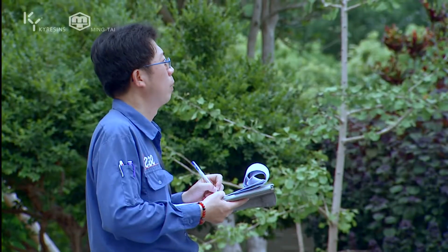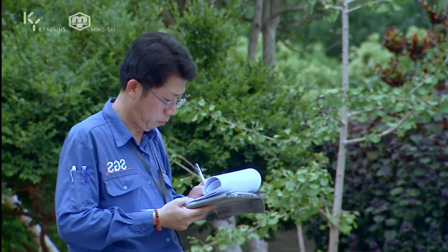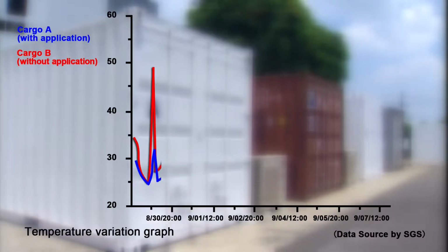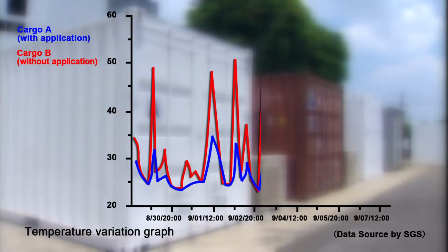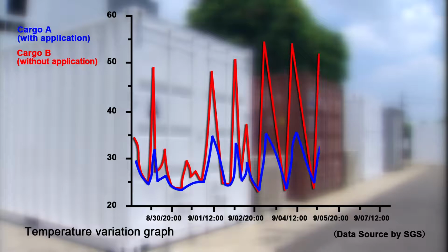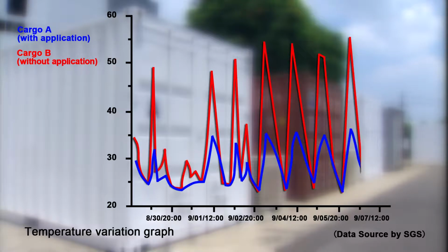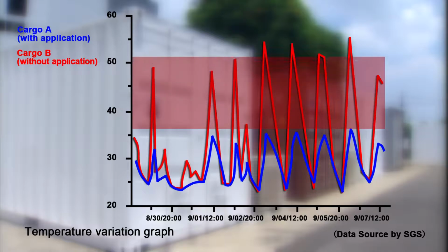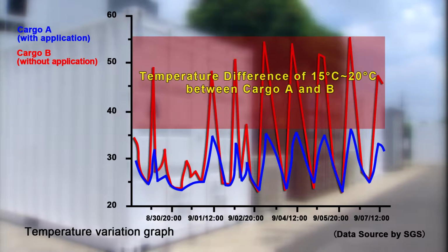Under circumstances of a 9-day temperature observation with no air conditioning, Cargo B without coating appeared to be the one with the most temperature difference of 25 degrees centigrade between day and night, whereas under the direct sunlight without any shade, Cargo B without coating tended to have significant temperature differences of 15 to 20 degrees centigrade from Cargo A with coatings.